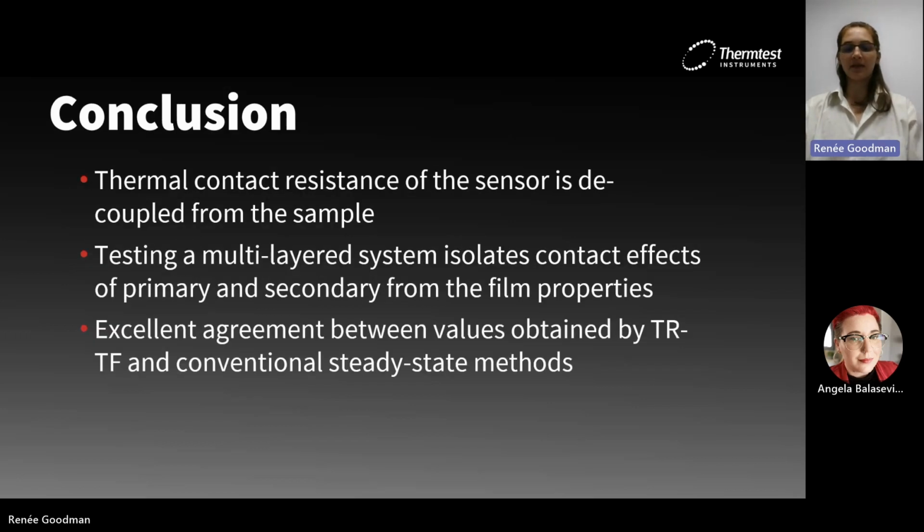So in conclusion, this is a method that is far more convenient and uses less material than our steady state counterparts. And most importantly, it decouples the contact resistance between the sensor and the sample and eliminates the need for a reference test, which is something that we don't see in any other thin film method. Secondly, using the multi-layered technique, we can basically isolate the contact effects and examine those contact effects or simply the intrinsic effects independently if we want to. And lastly, we get excellent agreement between these values and those observed in the steady state methods.